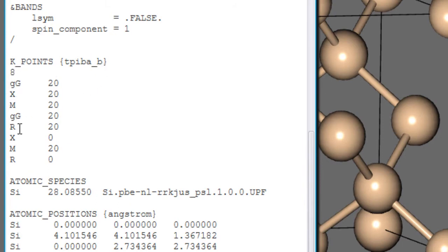So that is why you have the path. Now the newer Quantum Espresso gives you the ability to, instead of writing the complete coordinates of the gamma or the X point, just write short notations for all these high symmetry points. So for gamma or any Greek letter, you can just write the lowercase version, the letter in lowercase and then uppercase. So basically gamma corresponds to G, small g, and then capital G, and then X, M, and then gamma.